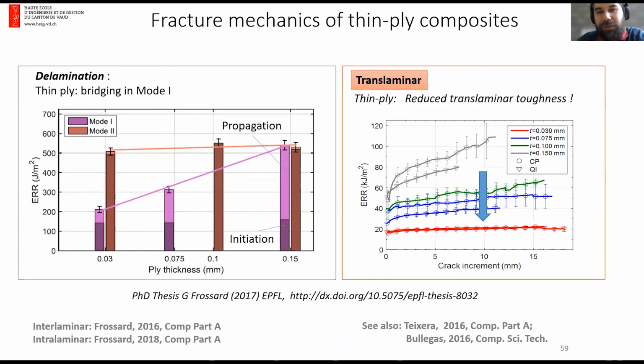In terms of translaminar fracture, Thin-Plies are weak. So when you have a crack going through a laminate, typically in open hole fatigue tests, for example, where cracks tend to grow sideways, we have a much reduced translaminar toughness with Thin-Plies. This is something to be considered. It can be critical. The effect is more or less proportional to ply thickness, so it's not a small effect.